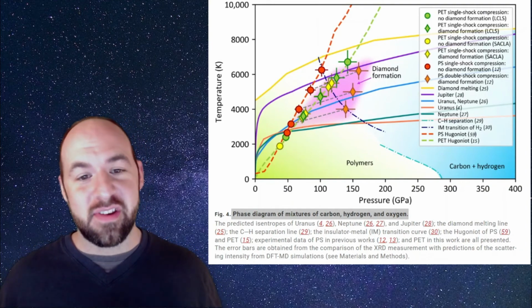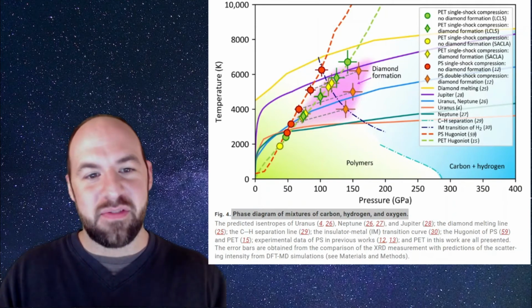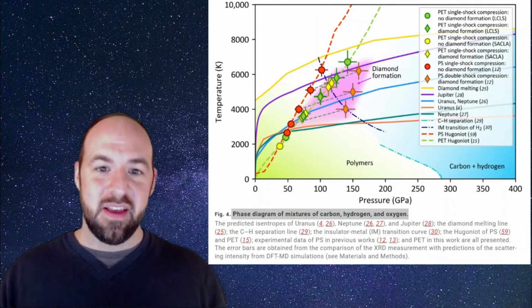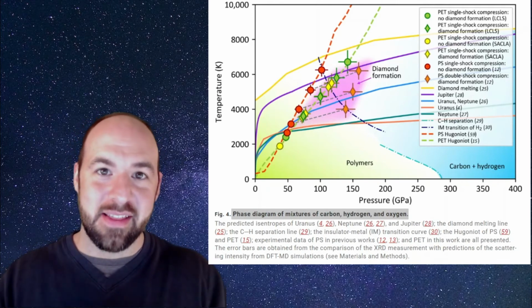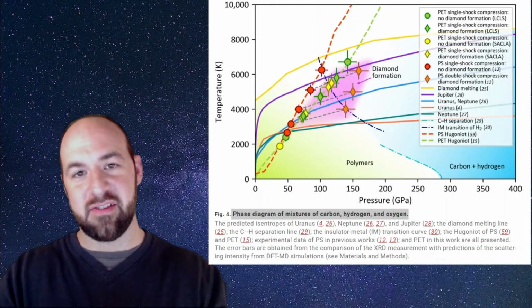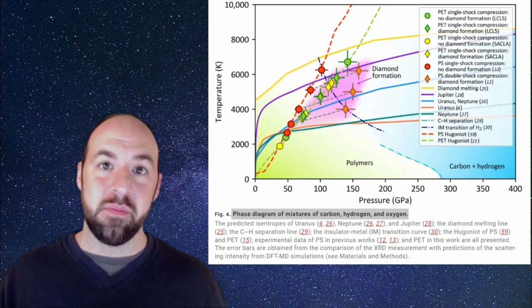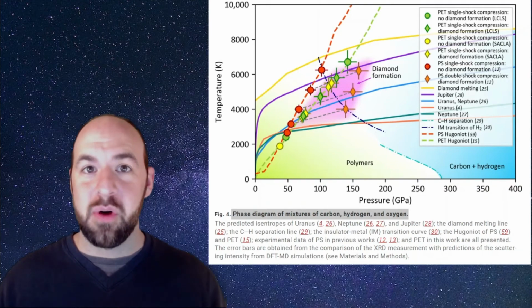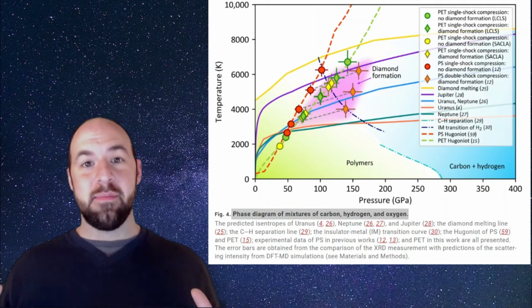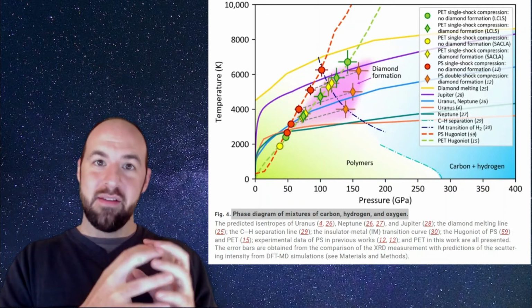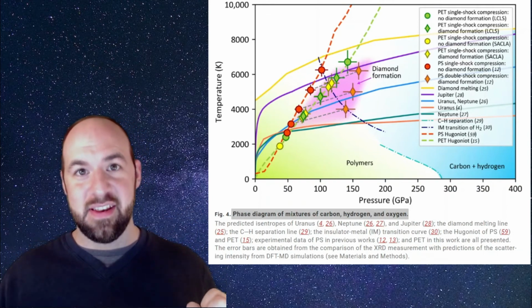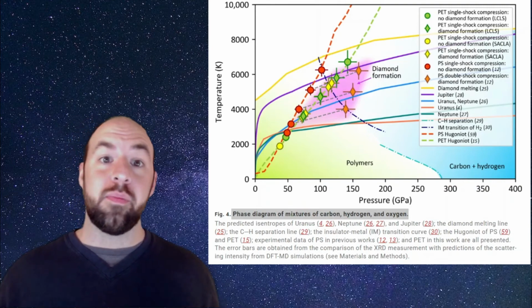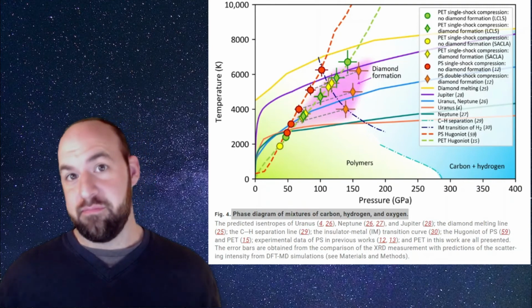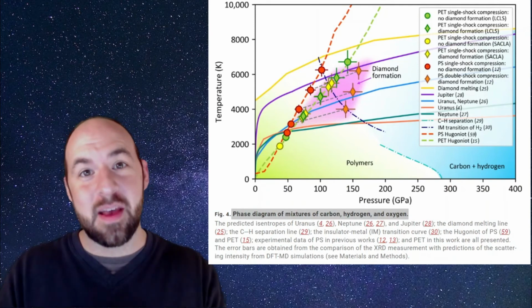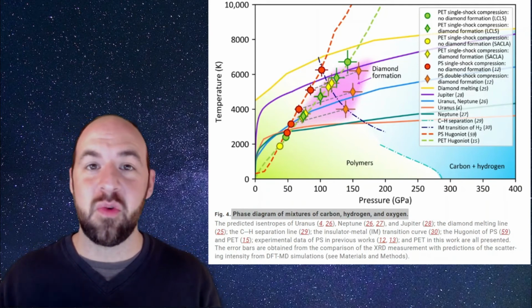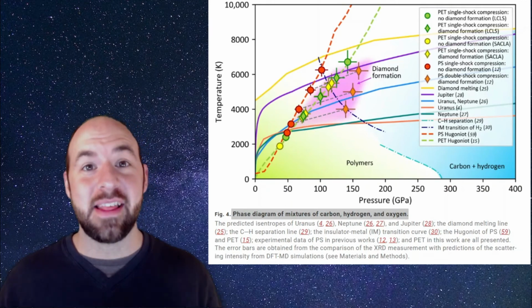Well, the idea that's very interesting to me is that, like the atmosphere of Uranus and Neptune, which has a mixture of different things, what we're showing is that by blasting this particular mixture that has carbon, oxygen, and hydrogen, you're able to actually form the nanodiamonds. And the nanodiamonds are composed of 100% carbon. And so what that means is the carbon is separating away from the hydrogen and the oxygen, and you're getting the chance to form water or potentially metallic hydrogen or oxygen. In turn, these phase-separated materials, this metallic hydrogen or the superionic water, are highly magnetic materials.